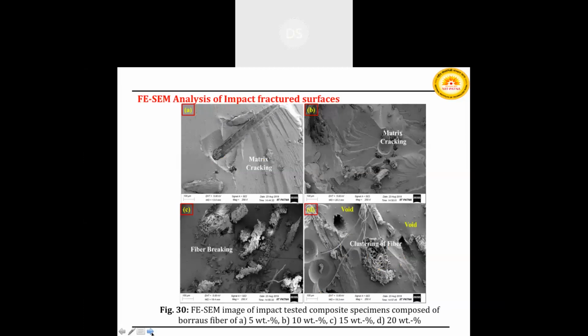During the impact test, as a certain load is applied on the notched specimen, the crack propagates throughout the specimen in 5% Borassus fruit fiber composite because fiber is less as compared to matrix. In 20% Borassus fruit fiber composite, fiber is pulled out, and the fiber matrix attachment cannot make a significant contribution to the energy dispersion during the composite fracture. During load operation, fiber could be easily removed from the matrix, resulting in weaker stress transfer, resulting in low impact capacity.